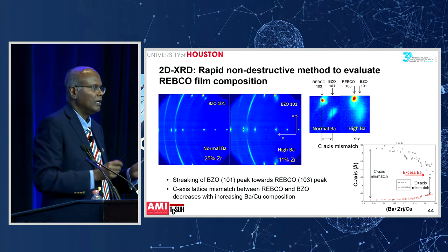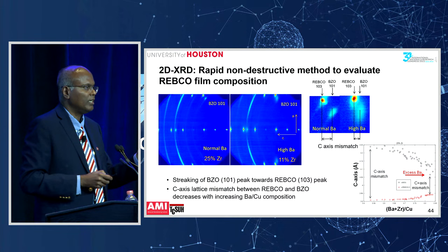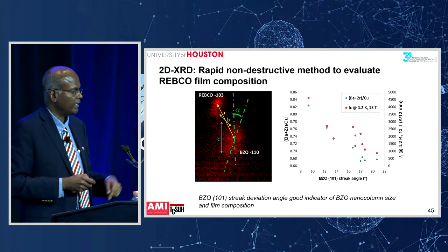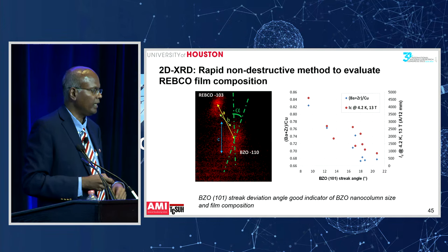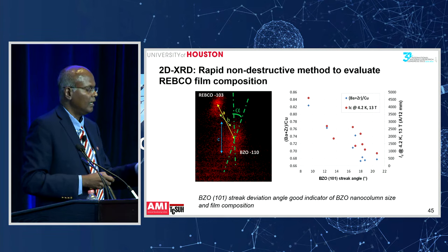So by monitoring the angle between the two, you can actually get a good idea of the composition, right? So that's the idea. You can actually see that in this chart also. You can see that angle, we call the streaking angle, between the two peaks. As the angle reduces, you can see the barium content in the film is actually higher. And consequently, and because of that, of course, the performance is also better.